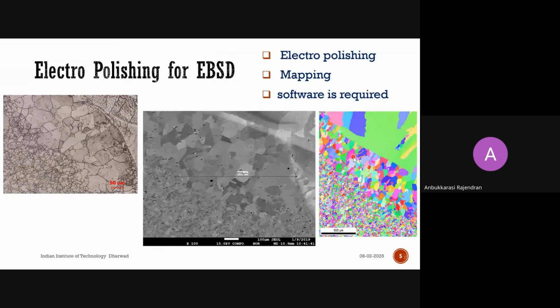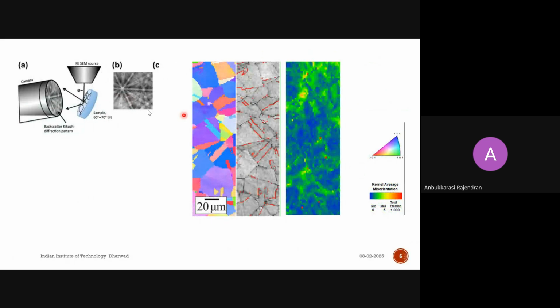So all the information related to the orientation and size distribution, everything we can get by using suitable software. Whatever we scan with the SEM machine with the support of the EBSD detector, those data should be run through some suitable software to see all the details, and whatever is required from this you can plot. As I mentioned, the goodness of the polishing, the surface finish, can be identified by the Kikuchi pattern. Once the electropolishing is done, if you load the sample into the machine, you can just hit the point with the electron beam. If it can produce a proper Kikuchi pattern, then I can ensure that my surface finishing is good.